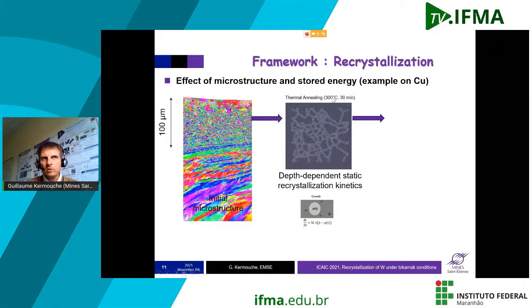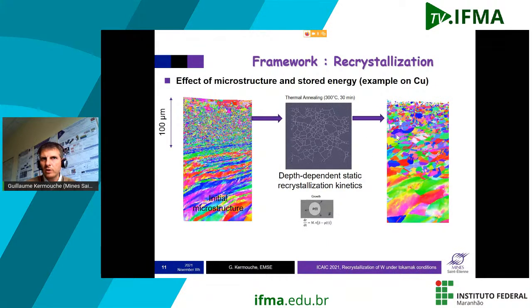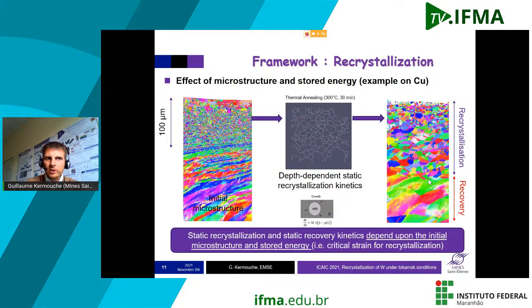If you apply a heat treatment of 300 degrees Celsius during 30 minutes, here are the results you obtain in terms of microstructure. You can see that the resulting microstructure depends on the depth. Here you have some small grains, here the grains are larger, and here we have no recrystallization. This is only recovery. So recrystallization happens here and recovery is here. That is to say that static recrystallization and recovery kinetics depend upon the initial microstructure and the stored energy. So if we want to deal with the recrystallization kinetics and optimize PFU, we have to optimize the initial microstructure of the material.